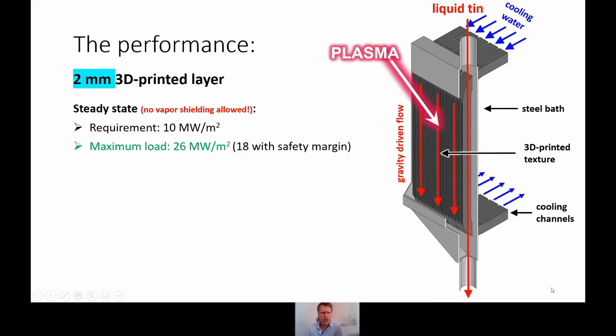We are required to dissipate about 10 megawatt per square meter. And it seems in this case, we can do it. So while keeping below our evaporation limit, which is in fact a surface temperature limit, we can dissipate about 26 megawatt per square meter. If you put a safety margin on that, there is still 18 left. So this is very good.